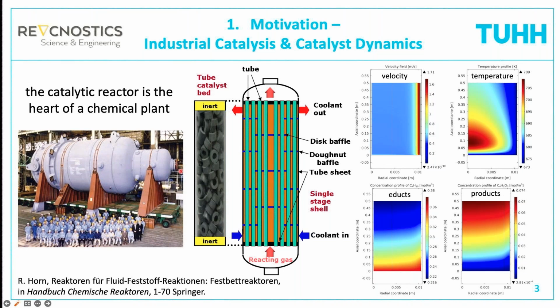these devices. So the mechanical construction principle can vary. I'm showing here to you the most often used type of catalytic reactors, the so-called multitubular catalytic fixed bed reactor. So the catalyst is here distributed into thousands of single tubes. Each tube has maybe a diameter of 2 to 3 centimeters, and then the catalyst is shaped into porous pellets. So this is needed, otherwise the pressure drop would be too high across the tube, and the porosity of the pellets is needed to have a high surface area for the catalytic reaction.